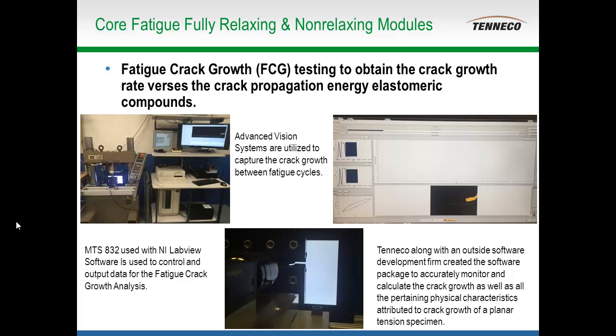So getting into more of the new test methods that are required for FE-safe rubber. There is a core fatigue module, and as Dr. Lee talked about during the keynote this morning, measuring the fatigue crack growth rate versus the energy release rate. This is not an easy test to perform. It's something that we've spent the past 3 years developing, the test hardware and software side, to be able to do all of the vision processing that's needed to measure the crack length.